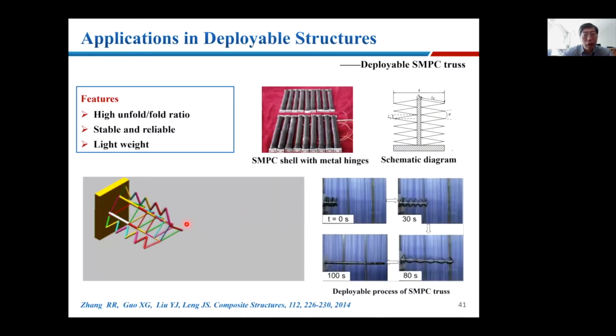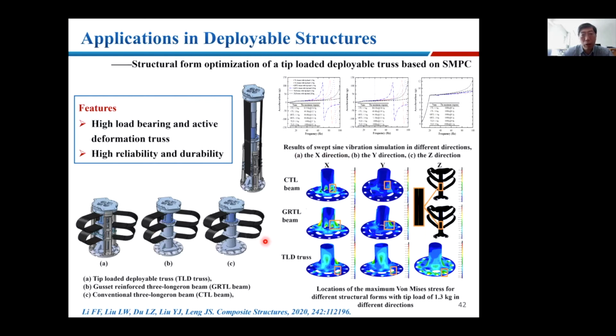This is another example, a truss. You can see the truss can also deploy simply by shape memory polymer plates like this one. From 0 seconds to 80 seconds, 100 seconds, you can see the truss can deploy. This is our more recent work, with this design. You have a few plates, and with this kind of design, when you're heating, this can deploy simultaneously. Then you can see the truss can deploy. This one was published in Composite Structures.